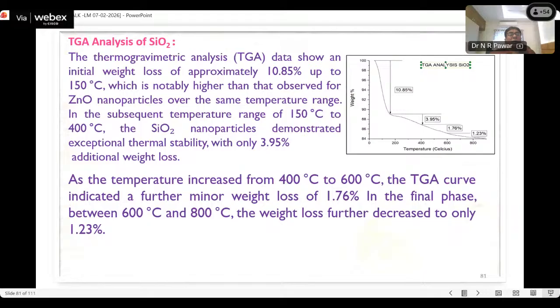This is the TGA analysis of the SiO2, and here it is observed that the initial weight loss is 10.85% up to 150 degrees Celsius, which is notably higher than that observed for ZnO nanoparticle over the same temperature range. In the subsequent temperature range, the SiO2 nanoparticle demonstrated exceptional thermal stability with only